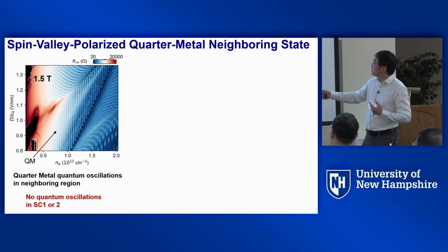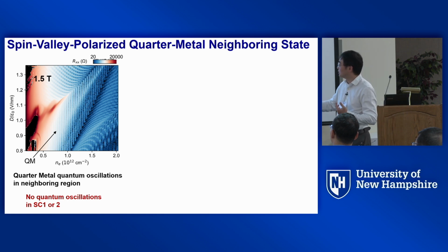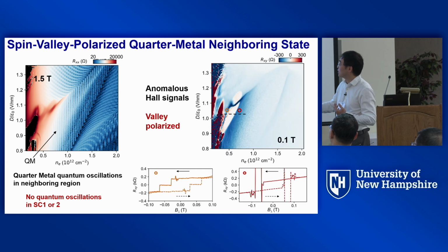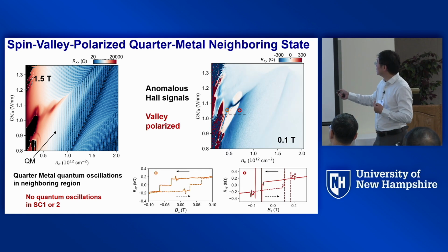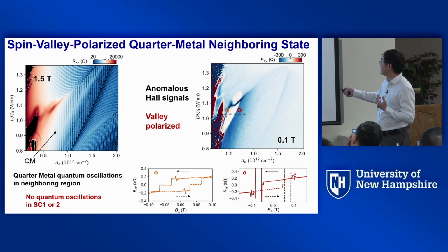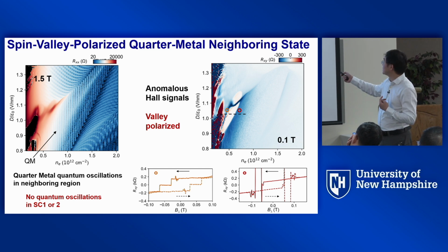Well, we have quantum oscillation reasonably well defined here with a very small period, while the period in other regions is bigger. I'll tell you what this period means later. And the second thing you can do is to ask, for this metallic state, even at 0.1 Tesla, you can probe its property, right? You can probe its resistance and probe its anomalous Hall resistance, okay? And clearly, this is a region that has a lot of anomalous Hall resistance, because the normal Hall resistance is at this color level at the same density, okay?